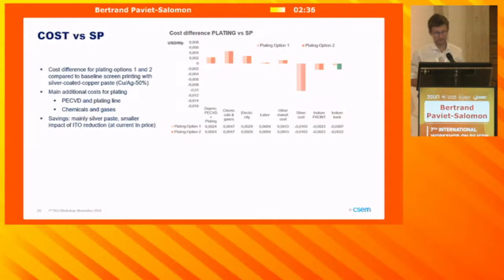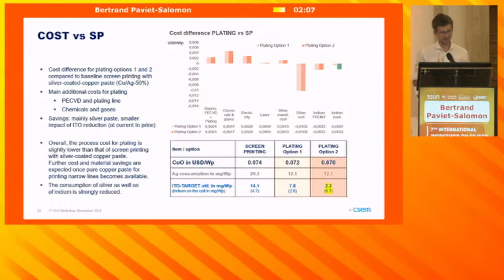And here you go. Let's say on the additional cost side for the plating, most of the costs stem from the fact that you have to add a tool for the masking layer and the plating tool, plus the chemicals and the gases to be supplied to those. Conversely, on the saving side, most of the savings come through the reduction of the silver paste, with the reduction in the ITO thickness coming as a second-order effect. Altogether, the process cost for our plating process was found to be lower than the reference.